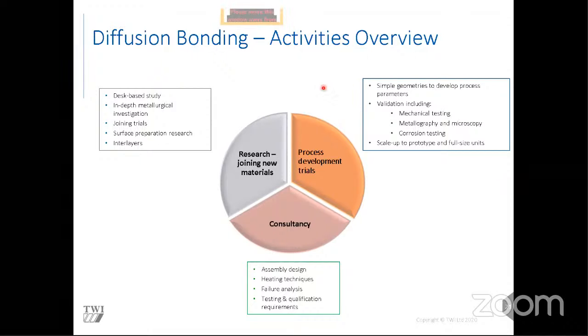So with the process development trials, we start off with simple geometries, and we develop our parameters. Then we go to larger heat exchangers. So we go from smaller to larger, because with the smaller samples, you're trying to develop your parameters and work out the strength of your bonds. We typically investigate our bonds by mechanical testing, metallography and microscopy, and even corrosion testing. And then we finally scale this up to prototype full-size units.